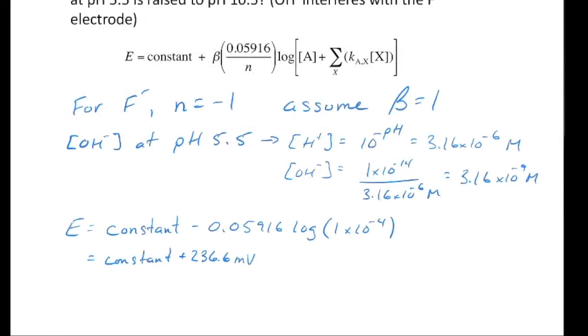Now what we need to do is to figure out what the voltage of the ion selective electrode would be at a pH of 5.5. So we have to know how much OH minus is going to be in solution and how much that interferes with the electrode itself. So the concentration of OH minus at pH 5.5. From the pH, we can figure out what the H plus concentration is. From previous chapters, we know that the concentration of H plus equals 10 to the minus pH. So that ends up being 3.16 times 10 to the minus 6 molar. And then we convert the concentration of H plus to the concentration of OH minus, and that ends up giving us 3.16 times 10 to the minus 9 molar.